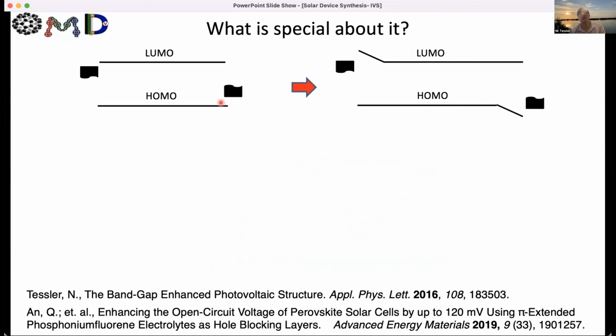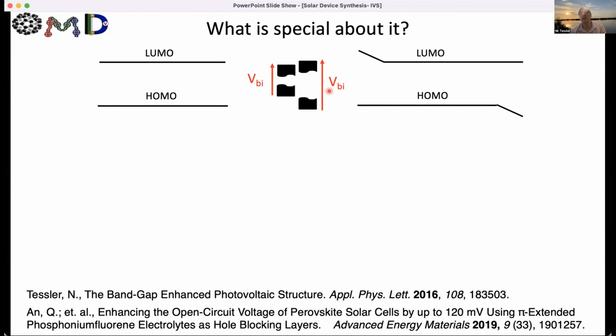So I placed here the two structures. We know that the electrodes are pinned relative to the band, so I kept the pinning relative to the edge of the band similar for both contacts. But because we have this change in the energy level diagram, like what I mentioned as the barrier for extraction, we can gain a higher built-in potential, which is the distance between the electrodes. So if you put them all one next to the other, you immediately see that we have a higher built-in potential, and that allows us to enhance the open circuit voltage in this kind of device.